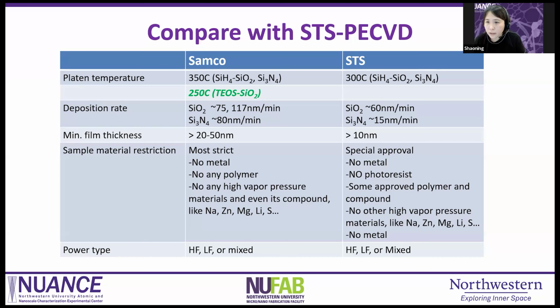New SAMCO is slightly higher, around 350 degrees C. And the STS is 300 C, but the temperature flexibility in STS is, the room is bigger for now. We have tried many other temperatures which still run well. So you can come to me if you want to run a lower temperature or a slightly higher temperature on STS, which is fine. For SAMCO, the temperature is pretty much fixed for each process. Silane-based oxide and nitride all run at 350. TEOS runs at 250 C.